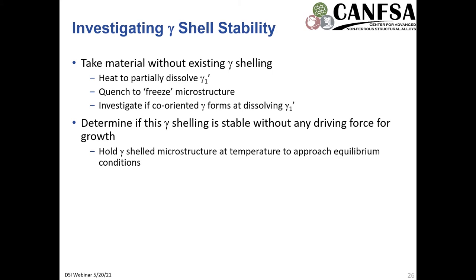And so one of the things that we're looking at is if you have a primary gamma prime that is dissolving, you'd expect the neighboring gamma grain to grow to consume that region that is dissolving. However, that may not be what is occurring, and we've seen some evidence of the contrary. And so what we've been looking at is to try to evaluate the stability of the shell as we dissolve the primary gamma prime. We're heating to partially dissolve this and then quenching to try to freeze the microstructure and investigate if this gamma shelling is stable. And then subsequently, we're looking at determining if this gamma shell is stable without any driving force for growth and if it would likely stay there at extended heat treatments.